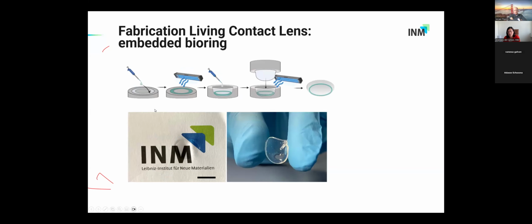We fabricate these contact lenses or prototypes in a two-step process. First, we fabricate the bio-ring, which contains the bacteria, and then we mold, as contact lenses are also produced in the industry, the rest of the lens so that the ring is embedded. The lens is transparent, you see here, and it's also flexible, with mechanical properties very close to your contact lenses.